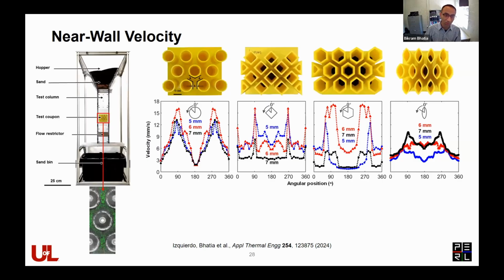So if the top is 0 degrees, you see that for circular tubes, right on the top and right on the bottom, on the top you have a stagnant region with low velocity, and on the bottom you have void areas. It's almost zero velocity, but on the sides you have a large velocity as you have streaming flow along the sides. You see slightly different behavior in this diamond shape lattice structure, where you have a much larger void area on the bottom, and you have much lower velocities on the slopes.